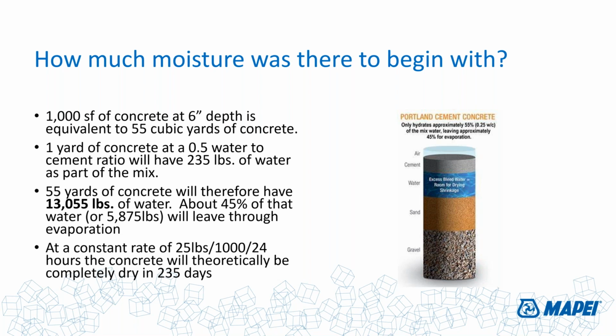So if a concrete slab has tested according to the ASTM F-1869 at a rate of 25 pounds per day in a 24-hour period, it's going to take 235 days for all that moisture to leave. And I think we've all seen a variety of different charts about how concrete dries and what the rate of evaporation is and why it takes, what's the number? I think it was 72 to 80 some days of curing to get it down to an 8-pound level, but quite a long time for a concrete slab to get to complete dryness. And it's really something that's never really going to get to that completely dry phase. It's always leaving.